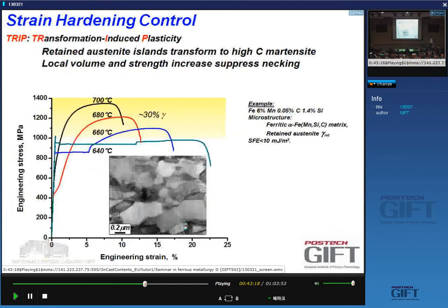Yes. Now, in terms of the manganese steels with the TRIP effect, they tend to be interesting, yes, because they have such a low alloy content in comparison to the two other systems, and because they have a low alloy content, they're easier to process, to weld, to cast, etc. So there is interest in these systems, but they're more complex because they have an ultra-fine microstructure.